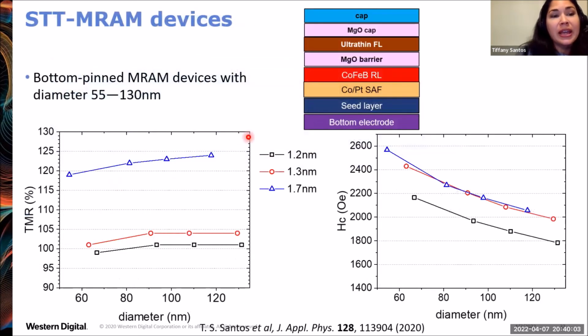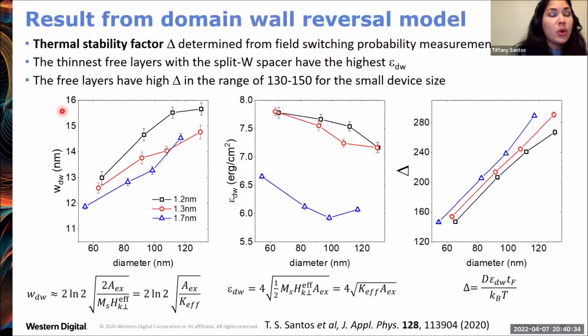We proceeded to make bottom pinned MRAM devices using these free layers. These devices were made by optical lithography. They have diameters in the range of 55 to 130 nanometers. And we saw TMR values in the range of 100 to 125% for these devices, and healthy coercivities for switching of the free layer approaching 2.6 kilo oersteds for the smallest devices.